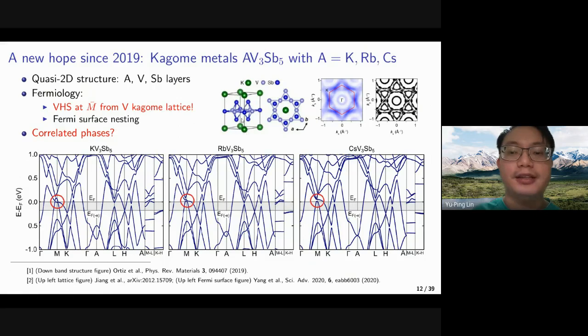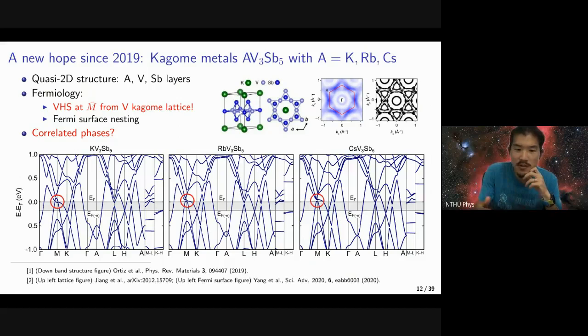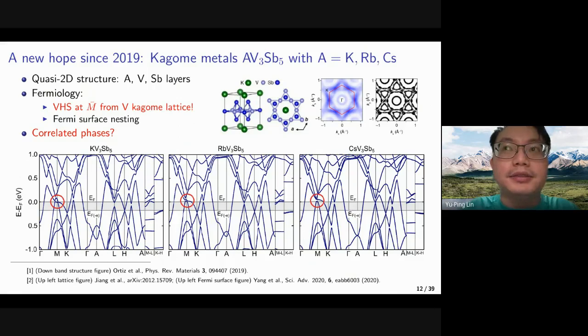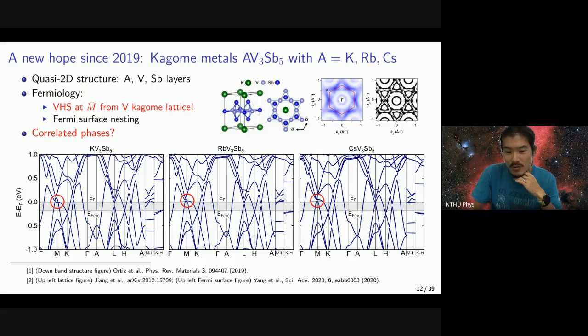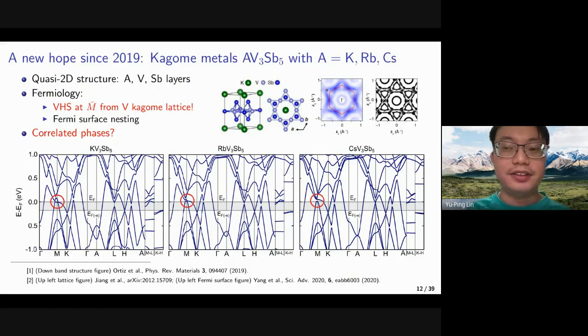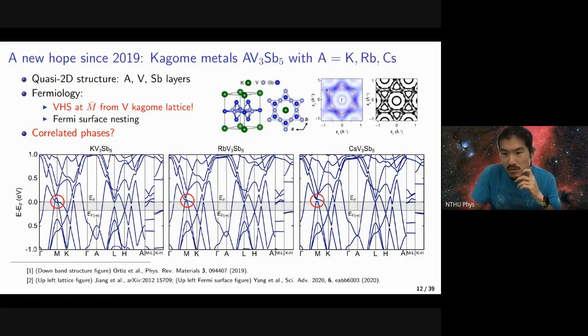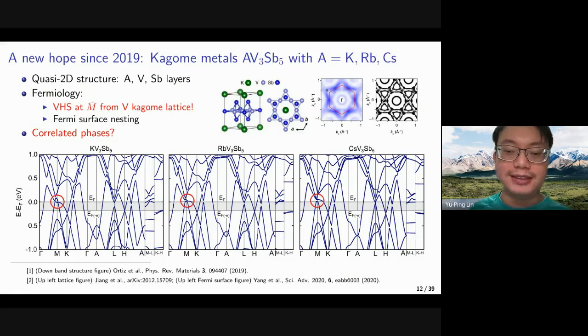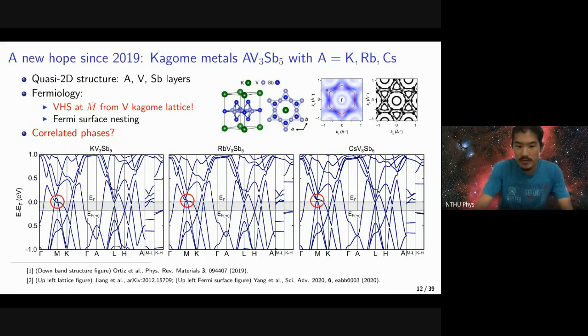So experimentally they measure a large anomalous Hall conductivity, right? It's not quantized, or it should be proportional to the thickness, right? In terms of your model, each layer will count one quantized Hall conductivity. So yeah, that's true. So maybe there's a way to confirm this. Yeah, something like that. That's a good point. I think they haven't really compared different thicknesses, so that might be a good generalization from the current result. Okay. Yeah, thank you for that good point.